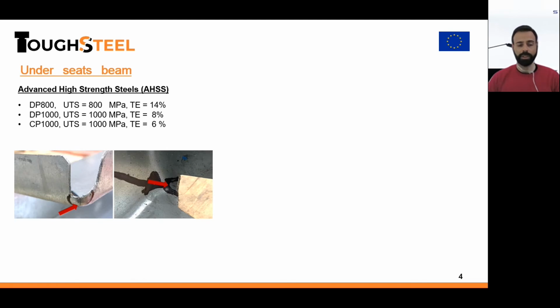During the projects, the vehicle design chose the DP1000 because it has a higher elongation than CP1000, and based on that, for sure, we will have higher global formability. But at the end, when we stamped the first component, we recognized an edge cracking from the border of the component. So to solve this issue, we tried to use the CP1000 grade, and also having less elongation, we were able to stamp the component without any crack.